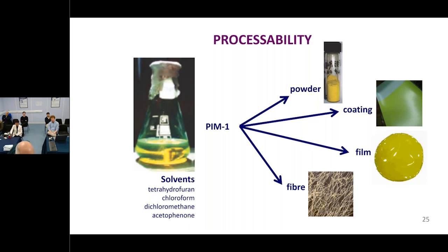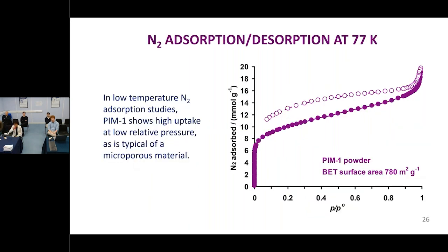And so one example of the way in which you might analyze a typical microporous material is by studying how nitrogen is adsorbed at low temperature. What you see here is at very low relative pressures, at 77 Kelvin, the temperature of liquid nitrogen, we get a very high uptake of nitrogen. And that's typical of a material with these very tiny pores that we're calling micropores.